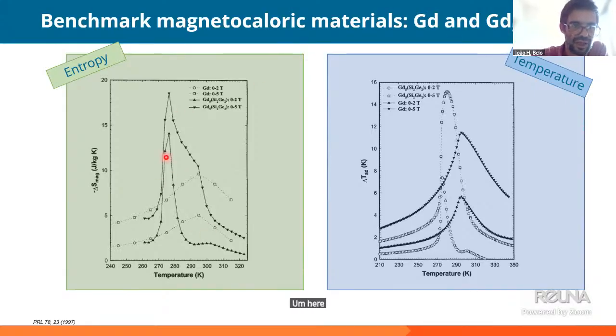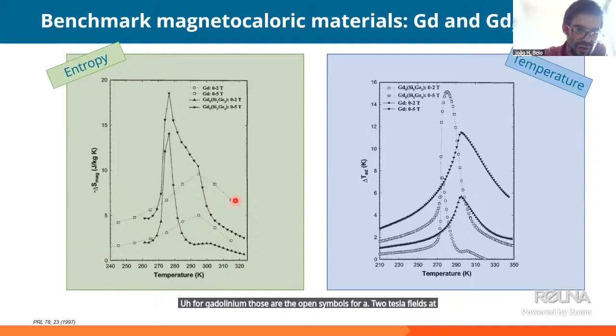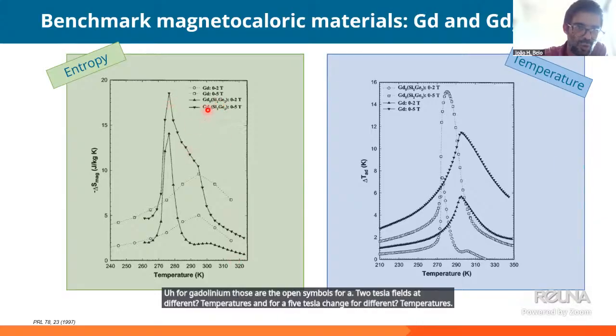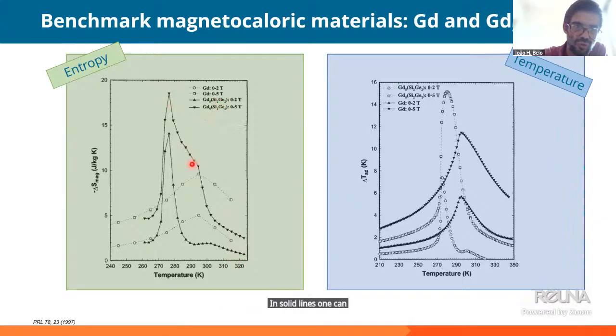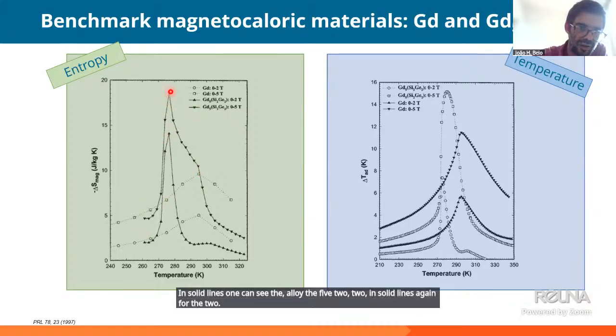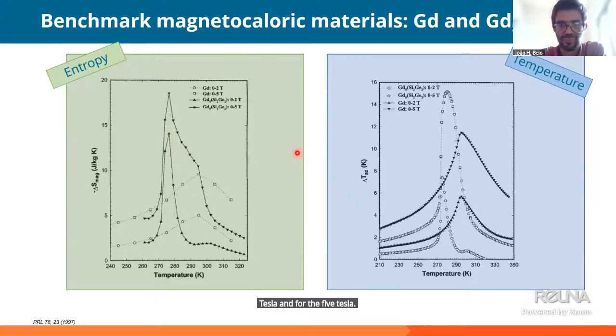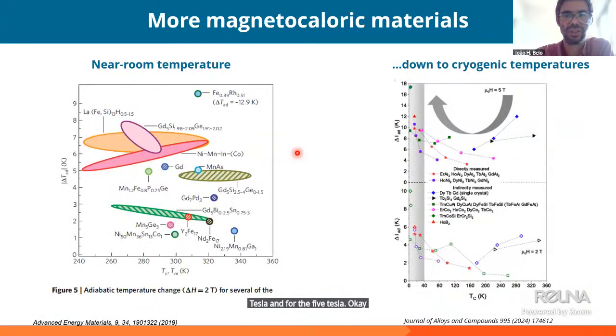Here on your left, one sees the change in magnetic entropy for gadolinium. Those are the open symbols for a 2 Tesla field at different temperatures and for a 5 Tesla change for different temperatures. In solid lines, one can see the alloy, the 522, in solid lines, again, for the 2 Tesla and for the 5 Tesla. Okay, there are much more materials.